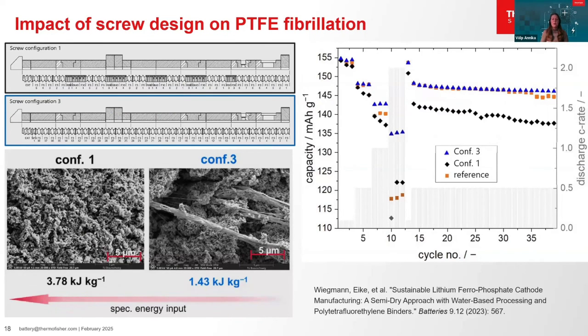The screw design determines the specific energy input applied to the material. Here you see two screw designs, with 5 mixing blocks and one without any mixing blocks. Below are SEM images of LFP cathode material mixed with PTFE using the two screw designs. The left SEM image shows the cathode mixed with 5 kneading blocks. The PTFE fibrils are small and well distributed. The right SEM image shows the cathode mixed without kneading blocks. The PTFE fibrils are much larger because the mixing here relies only on particle-particle interactions, and the lower energy input is insufficient to evenly disperse the PTFE.